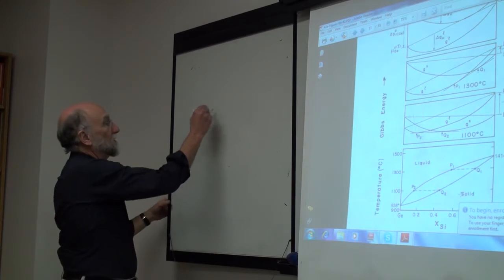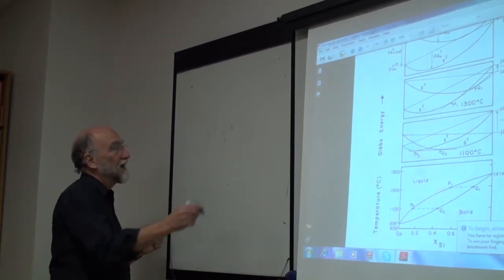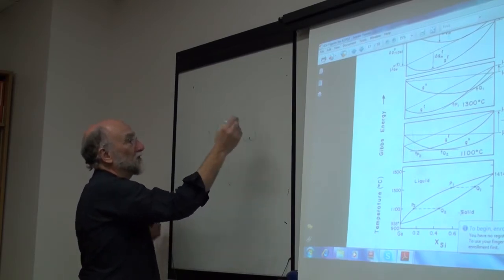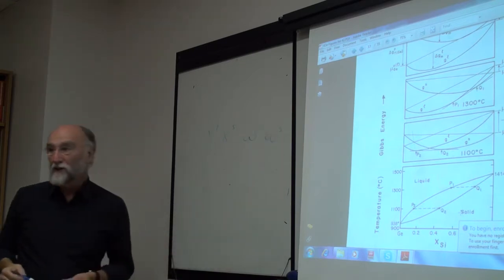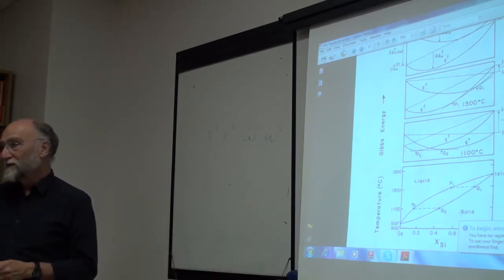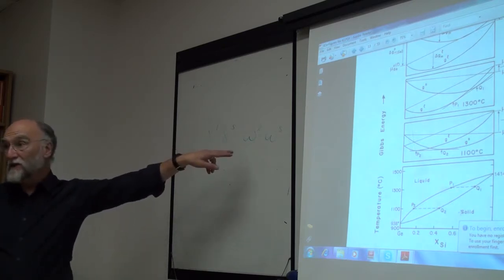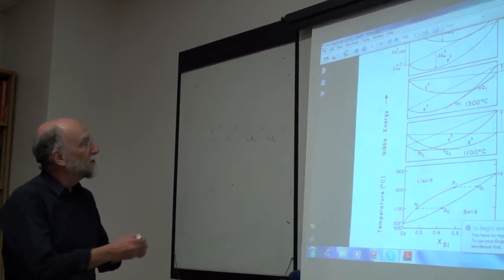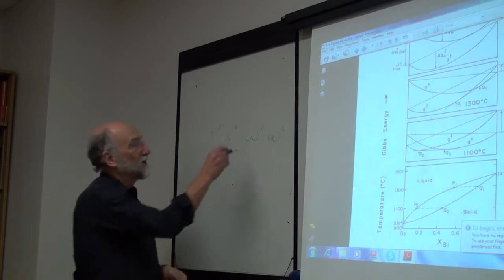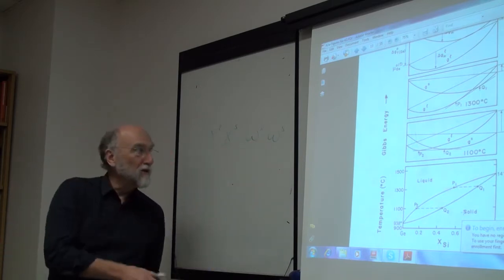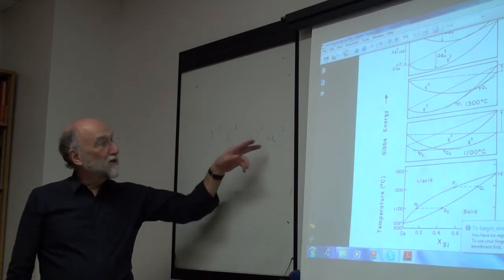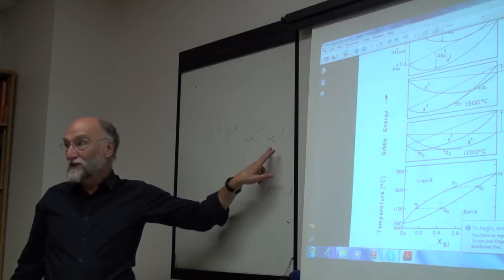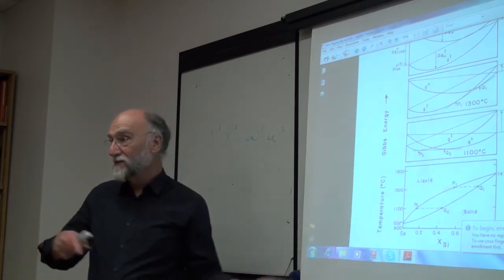There's the mole fraction of the liquidus, there's the mole fraction of the solidus, and let's say we have a regular solution interaction parameter for the liquid, and a regular solution interaction parameter for the solid. So your RT log gamma terms can be calculated. If you know what these are, you can then calculate the phase diagram. But if you have the phase diagram, now you know what the x's are, so you can go back and calculate your two omegas. So you can use the equations the other way. And of course you're assuming that both are regular solutions. Maybe that's not a good assumption, but if both of them are regular solutions, then the same equations permit you to solve the thing backwards.